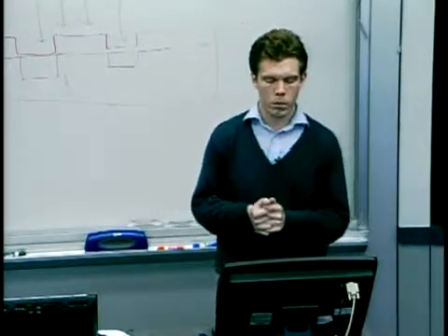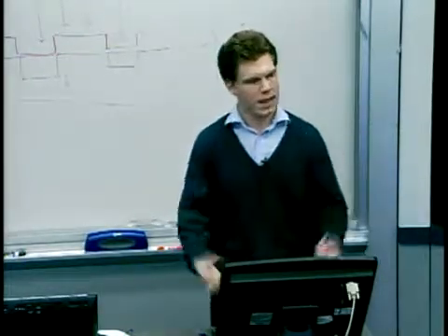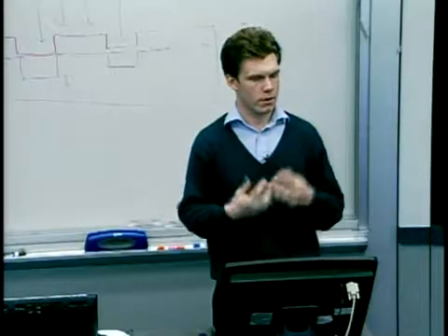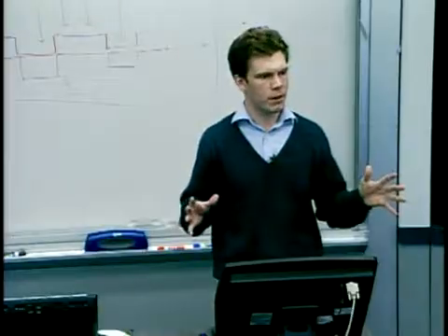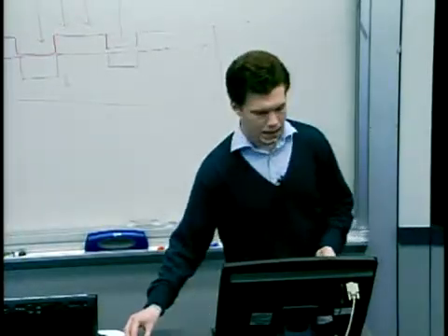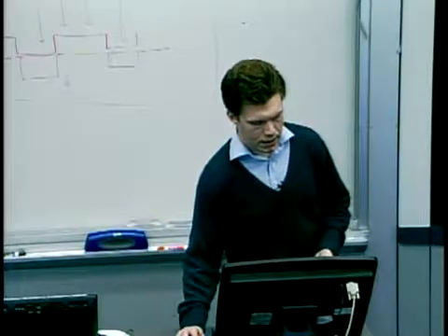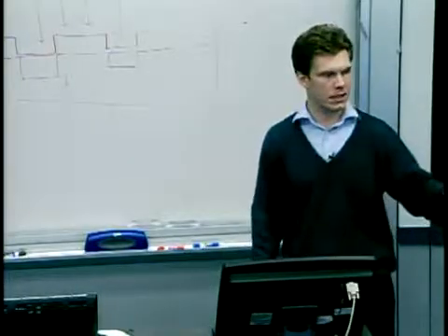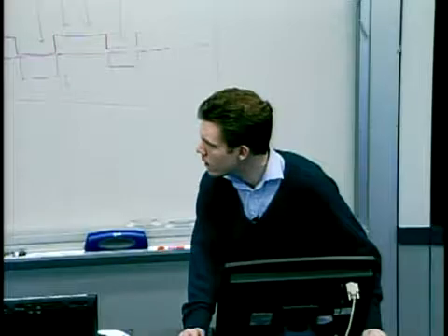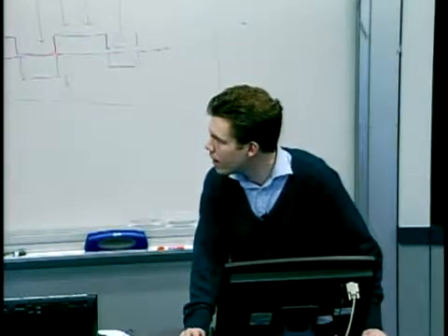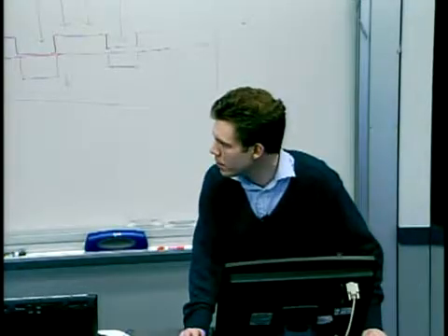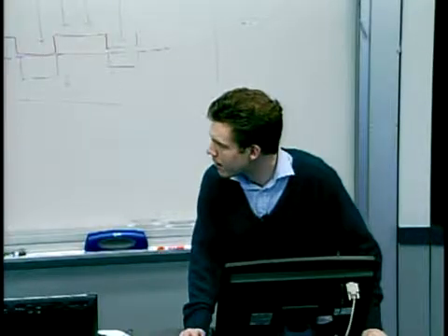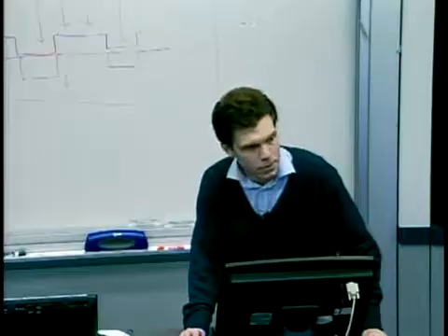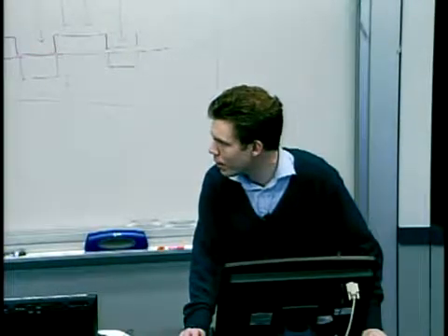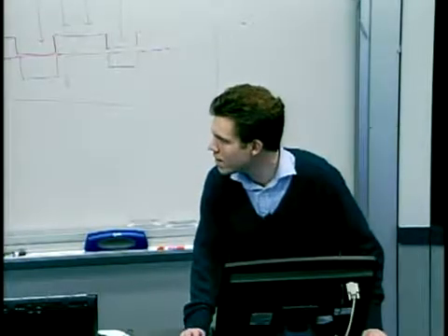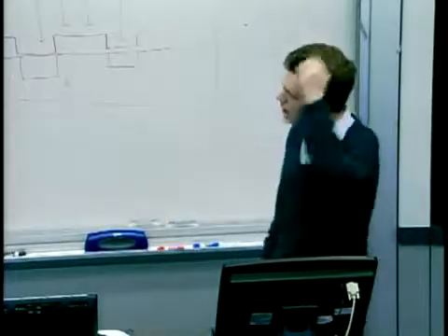So we had to think quite carefully about what type of characterization patterns to use in these experiments. We're trying to think of ways of doing a minimal number of experiments that will give us as much physical information as possible. And what we came up with was this. Here is a plan of the surface of a silicon stamp that we etched. And it's a square array of various patches of features. Some of them are parallel channels, some of them are square holes, and we have parallel channels running in both directions. So for every line to space ratio of channels, there's one set running horizontally somewhere, one set running vertically. And they were arranged in a random order across the stamp.